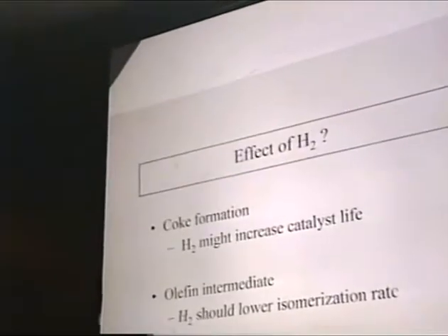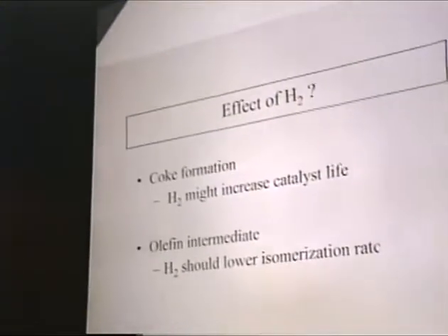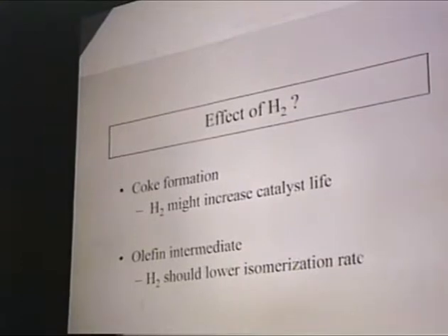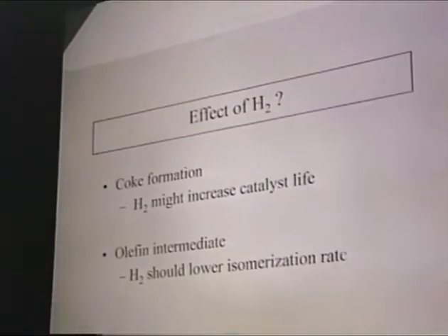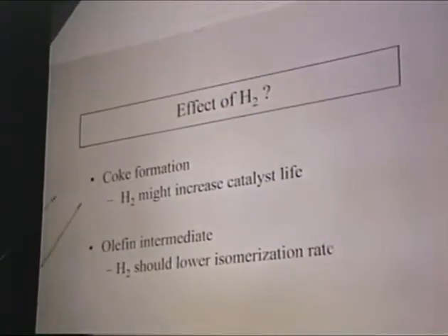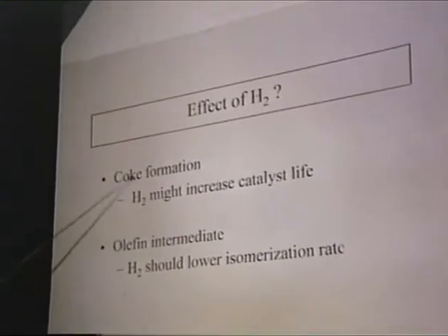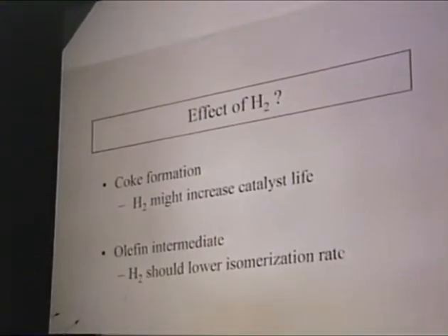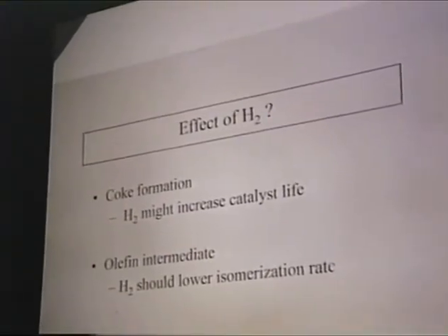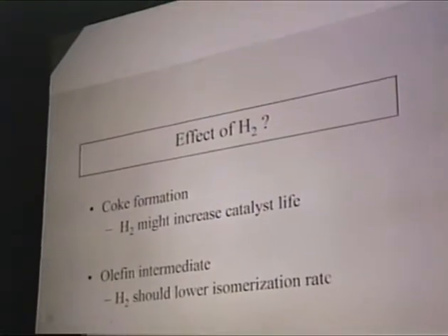Since we all know that this catalyst deactivates very fast, we were wondering what effect hydrogen would have on the catalyst, and we realized that the hydrogen may remove the coke and increase the catalyst life. And we also understood that we might have olefin in our mechanism, and that will slow the rate for this isomerization.